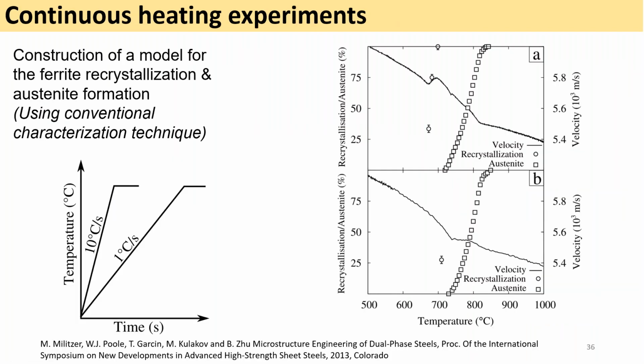Of course, in an industrial case, we are not interested only in isothermal holding, but we are interested in recrystallization occurring upon continuous heating. So that's what I'm showing you here. This is a little bit trickier because the recrystallization here will be seen as a change in velocity, like you can see here. And it's not always very easy to decompose whether or not this recrystallization occurs during or after the onset of austenite formation. So what we have done here is conducting a dilatometry study and a microstructure study to have an idea whether this type of signal could be used to infer whether the recrystallization occurs during the austenite formation, which is the case here.